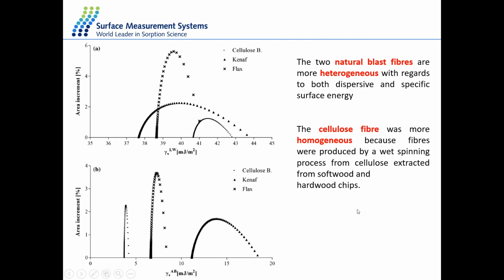So we've also done some surface energy experiments. These are the two distribution profiles. So we have the dispersive distribution here and the specific distribution here. And what we can see is the two natural bast fibers are more heterogeneous with regards to both the specific and the dispersive surface energy. So these peaks are much wider. And of course, because the cellulose fiber was produced by wet spinning, we can see that this contributes to a much more homogeneous surface.